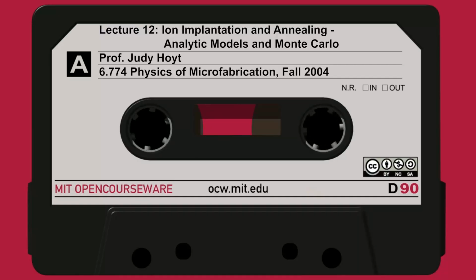And ions that are not channeled early in the process, as they get closer to their end of range, as they lose energy, the critical angle increases. In fact, I didn't mention that. If I go back one page to slide 28, this was Lindhard's expression for the critical angle. It depends on some constant E1 divided by E. So as I get slower and slower, the critical angle goes up. So the probability of channeling is going to be bigger at the tail of a profile. In fact, you see that on slide 30.